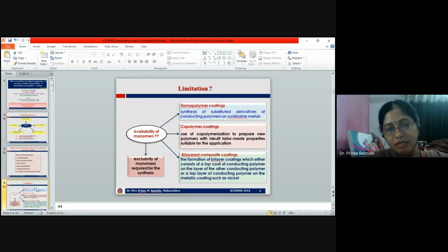However, there is a limitation in the availability of conducting polymers due to the exclusivity of the monomers. To overcome this problem, different synthesis approaches can be attempted. First approach involves the synthesis of substituted derivatives of conducting polymers on oxidizable metals. Second approach, use of copolymerization to prepare new polymers with inbuilt tailor-made properties suitable for the application. Third approach involves bilayered composite coatings.